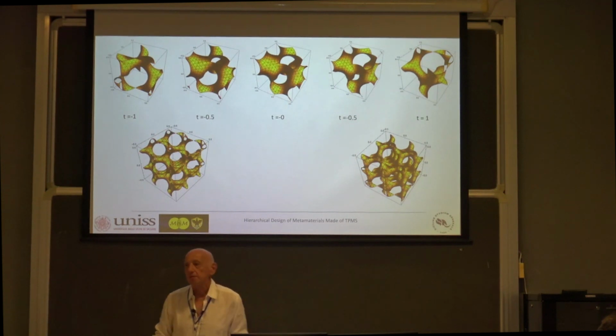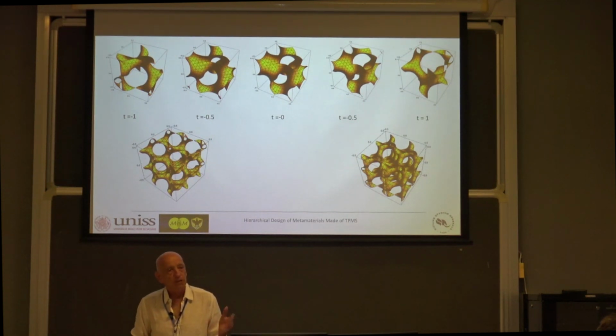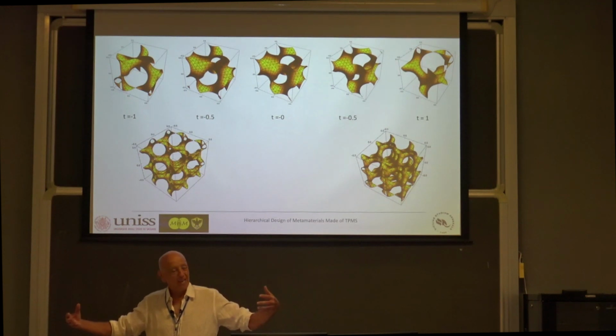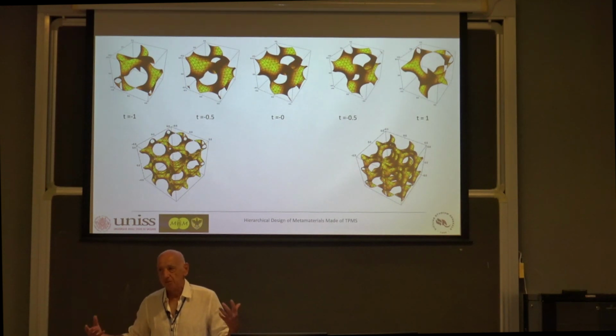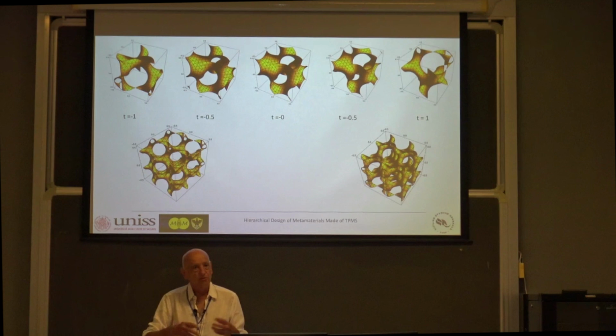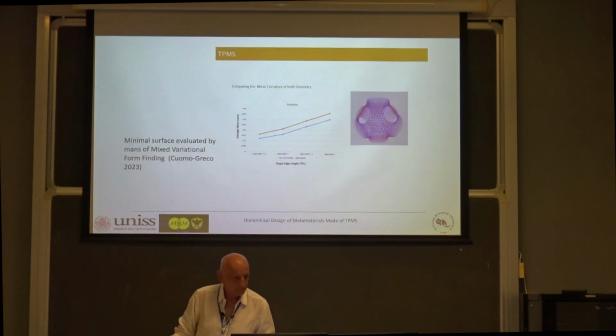This is, for instance, for the gyroid. What happens if this t parameter goes from -1 to +1? You can see it better in the bottom line. When this parameter is very large, you get an almost lattice-like material. So by changing this parameter, you can modulate from lattice to surface.